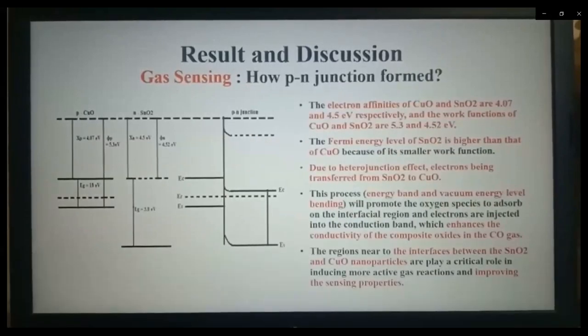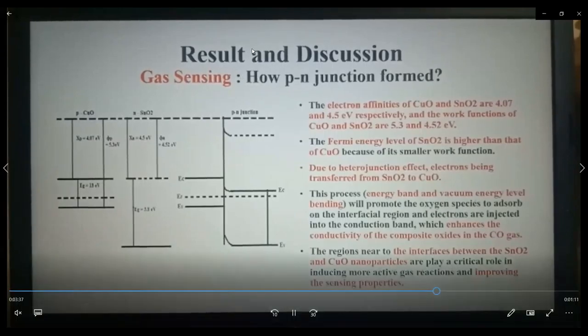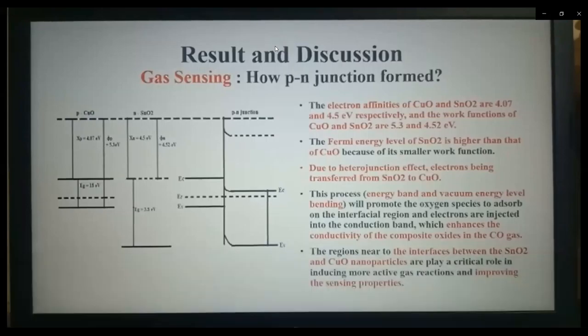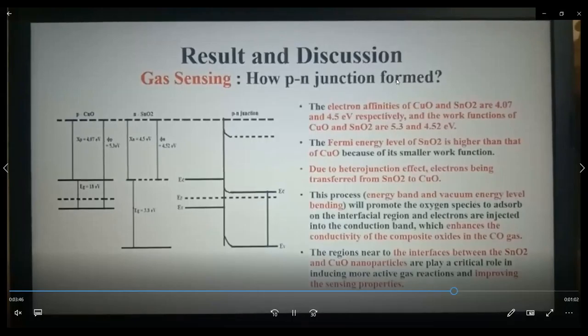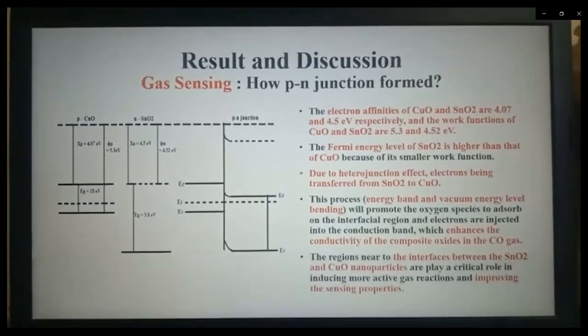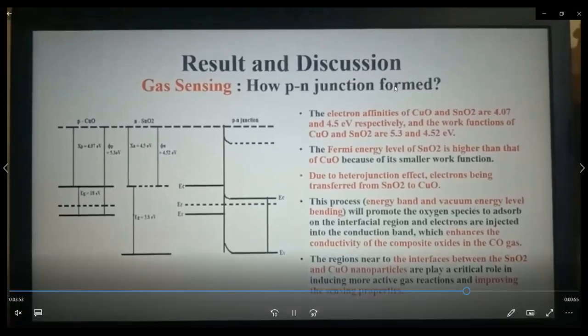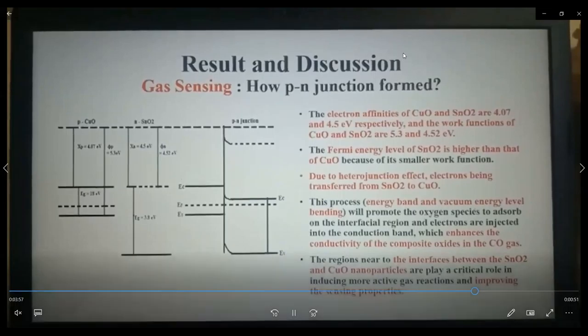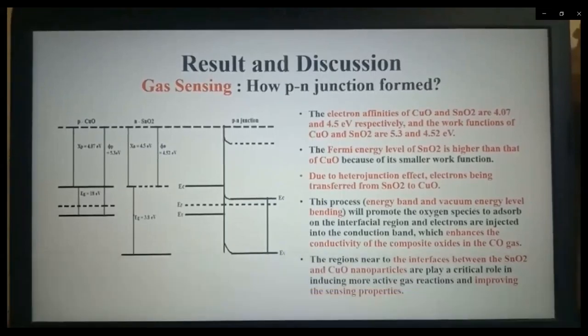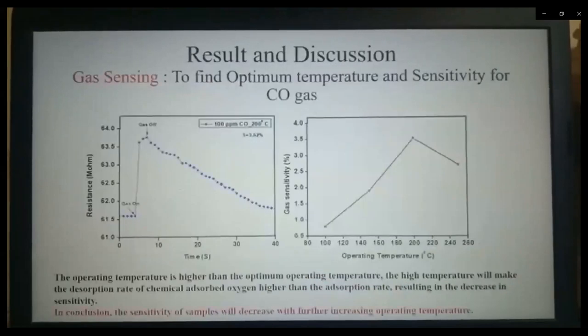Now why is a PN junction formed? Because we know that copper oxide is a P-type semiconductor, whereas SnO2 is an N-type semiconductor. So by using electron affinity and work function, it forms a Fermi energy level. Due to this heterojunction effect, electrons are transferred from SnO2 to CuO. And because of this interface, it improves the gas sensing property.